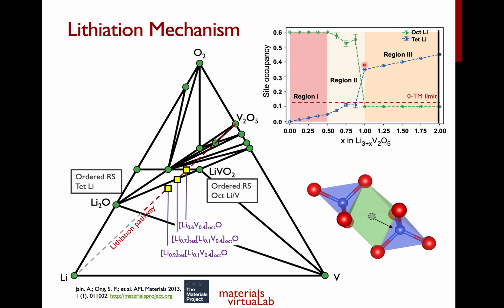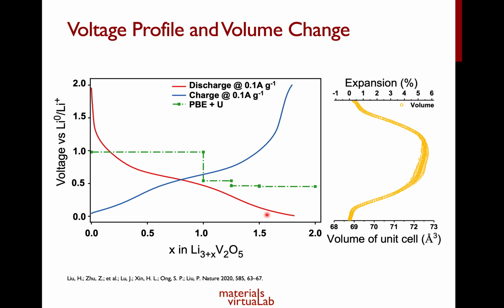Now, as we continue to lithiate from Li4V2O5 to Li5V2O5, basically all that happens is that you are increasingly inserting lithium into tetrahedral sites, and the occupancy in the octahedral sites no longer changes. That is basically region 3 over here. The endpoint, at least what has been experimentally achieved so far, is Li5V2O5, in which you basically have 0.9 lithium in the tetrahedral site. You only have 0.1 lithium in the octahedral site and 0.4 vanadium in the octahedral sites. So this is basically the lithiation mechanism, right? Now, from the lithiation mechanism, we can then compute the energies and construct the convex hull, and then calculate our voltage profile.